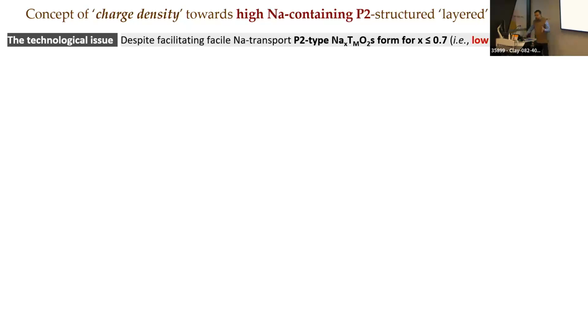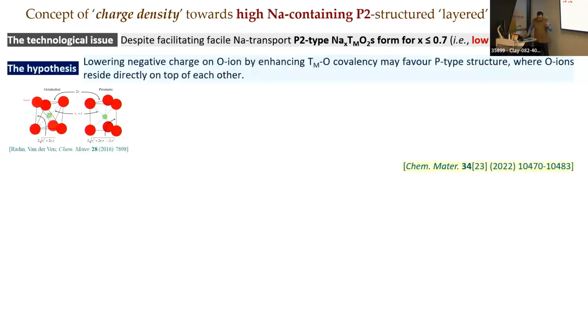A classical composition is Na 0.67, as low as that. Okay. So now, if we want to have the prismatic coordination stable, that is P2 type structure stable with higher sodium content, the best thing to do is first having a close look at the octahedral versus prismatic coordination. So that is what it shows here. This is my octahedral coordination, this is my prismatic coordination.